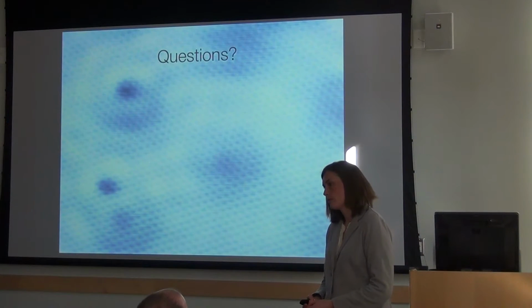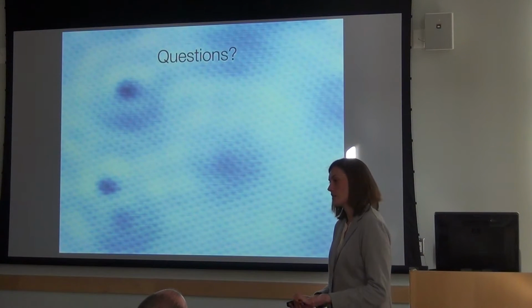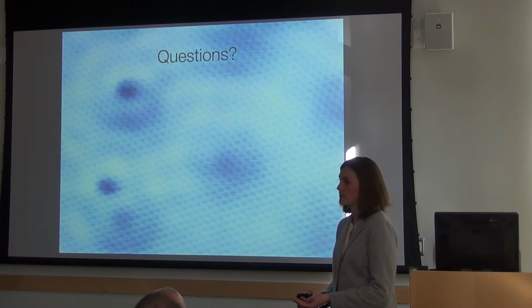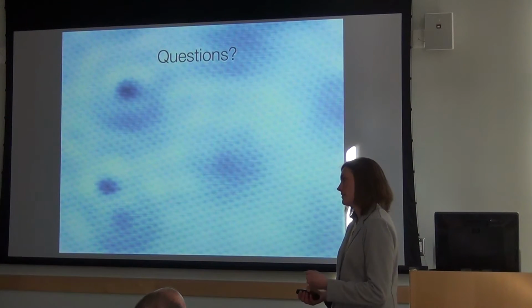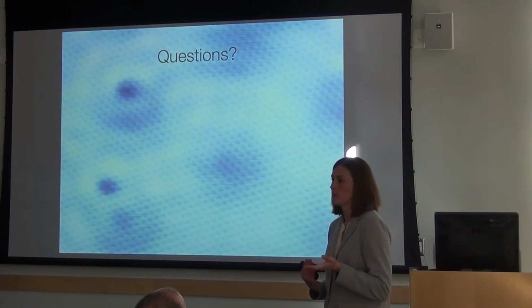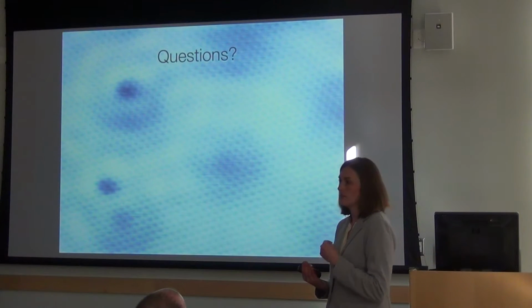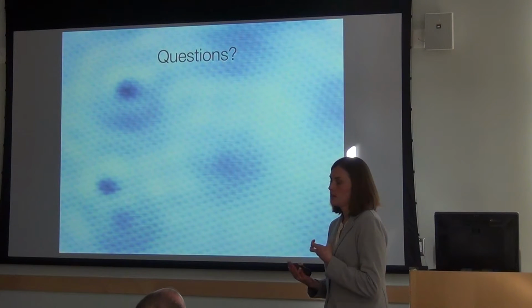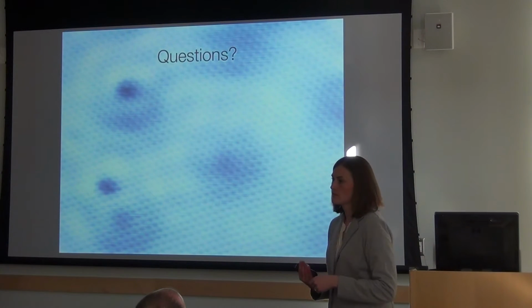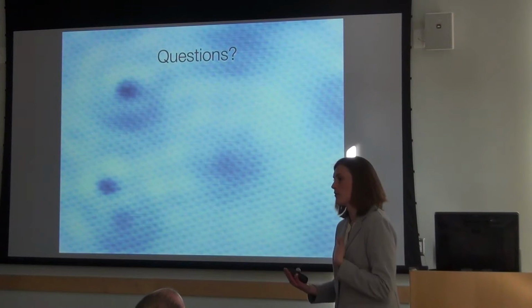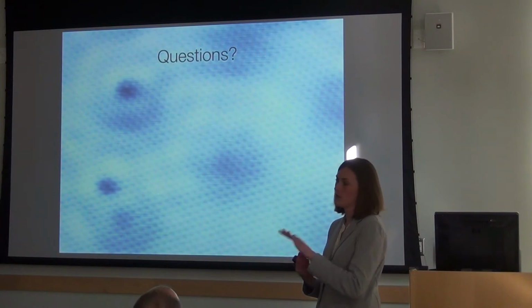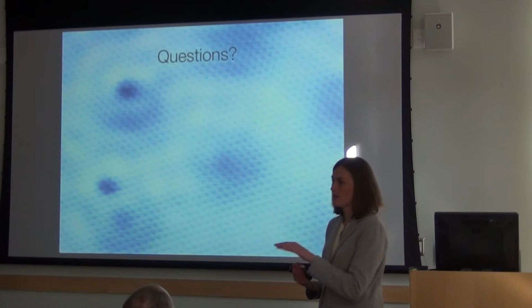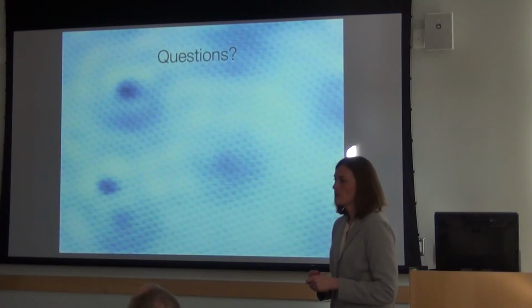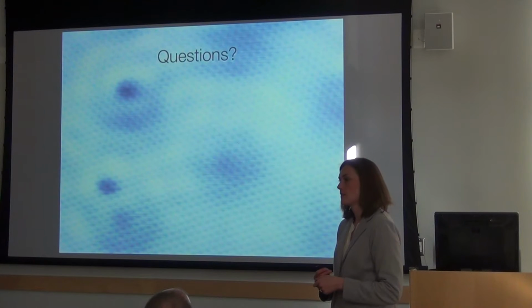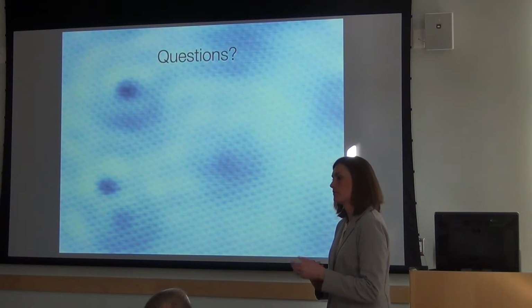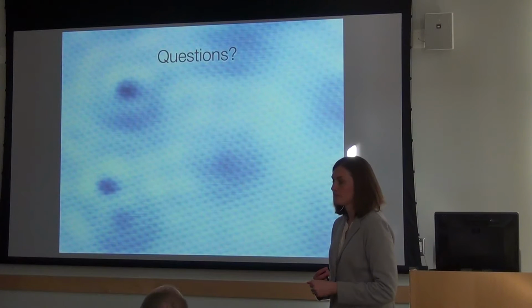What most people do, and the reason I think that our results are so different from what most people have found, is they pass H2 over a hot filament, and then they have atomic hydrogen impinging on their surfaces. And they can either accelerate it or don't, but they have some flow of gas that goes over a hot filament to crack it, and then it hits the surface later. So that's the main difference between what we've done and what other people have done.